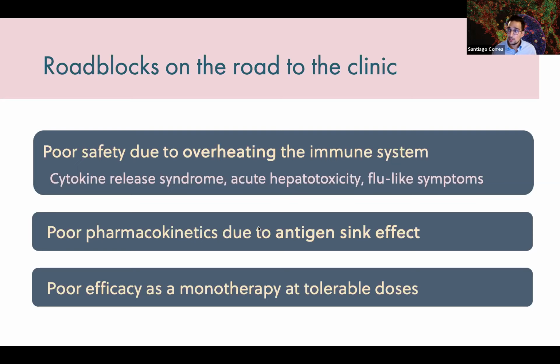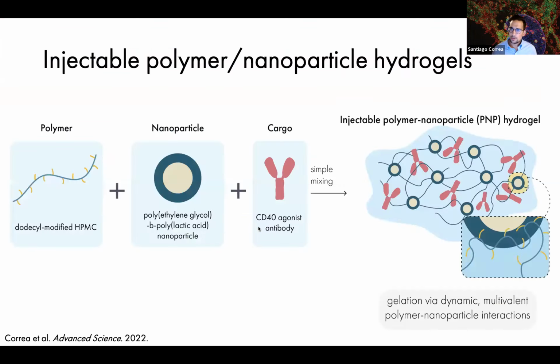And for an antibody, that's actually really bad. Normally, antibodies have circulating half-lives that can be on the order of a month. So these two issues combined have really limited the efficacy of CD40 agonists as a monotherapy. And so what I wanted to do was see if these nanoparticle-based hydrogels could be used to really unlock the potential of CD40 agonists, especially because right now there's a lot of renewed interest in these drugs for combination immunotherapy approaches.